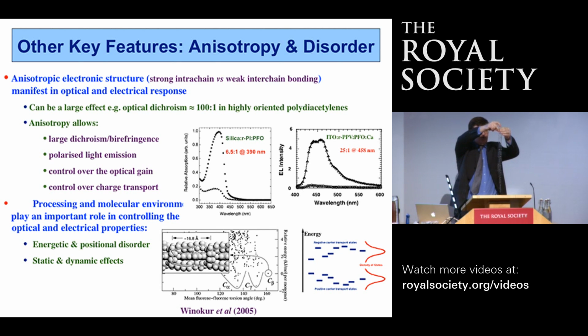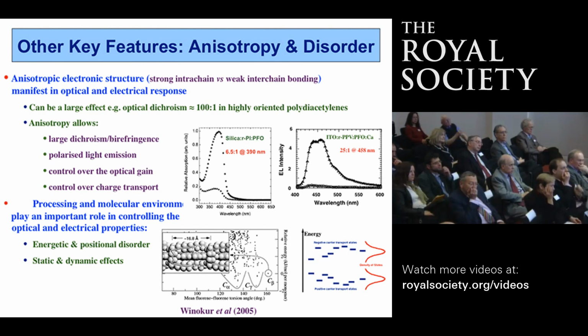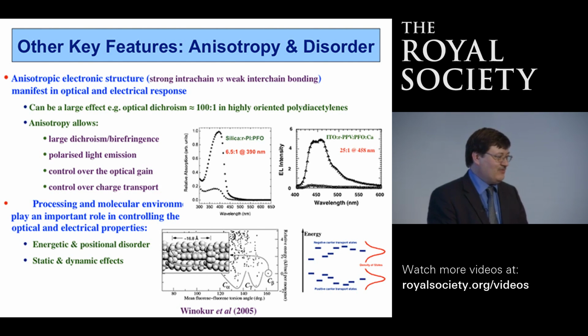We can do that in a number of ways. One is to make use of what's called a liquid crystalline phase for the materials, and we can arrange that they line up like this. And when they line up like this, they are very anisotropic. And so, for instance, if we look at their optical properties, they have a very strong polarization of the absorption and the emission. We can use that to make interesting objects, so polarized light sources. We also see that if we want to look at charge transport in these materials, it's much easier for a charge to move along that chain than neighboring chains. So if we make it anisotropic, we see quite strongly anisotropic transport.